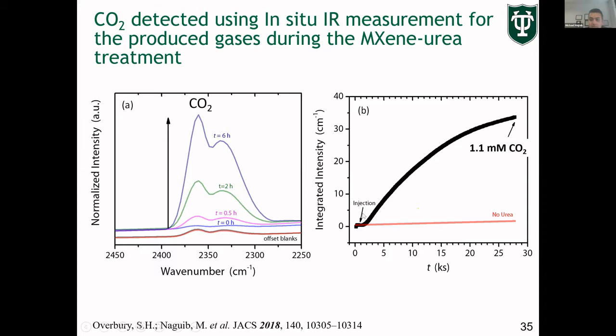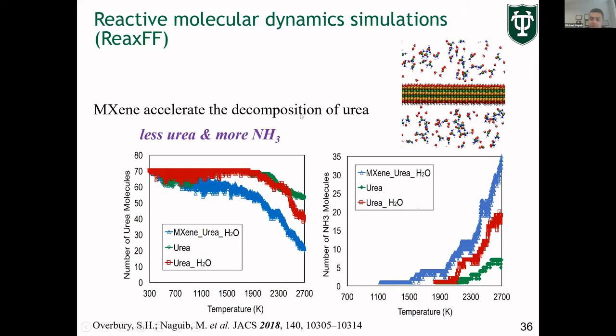So we really are forming some CO2. So we have some decomposition taking place of urea. And to check, while this has any basis from a theoretical point of view, we, in cooperation with Adri van Duin at Penn State, did ReaxFF and looked at the system for urea alone, which is green here, urea with water, which is red, and urea with water with MXene, which is blue.